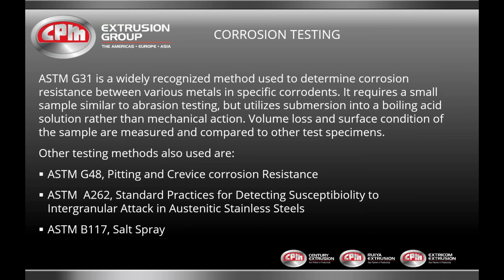For corrosion testing, ASTM G31 is a widely recognized method used to determine corrosion resistance between various metals and specific corrodents. It requires a small sample similar to the abrasion testing, but uses submersion into a boiling acid solution rather than mechanical action. It's measured the same way: volume loss and surface condition of the sample are measured and compared to other test specimens.